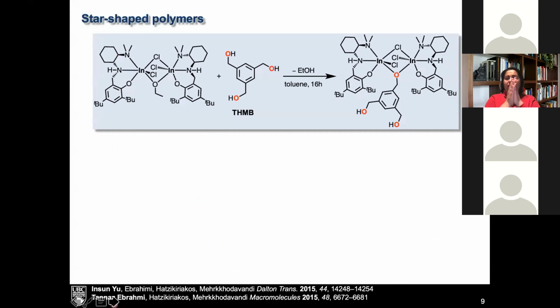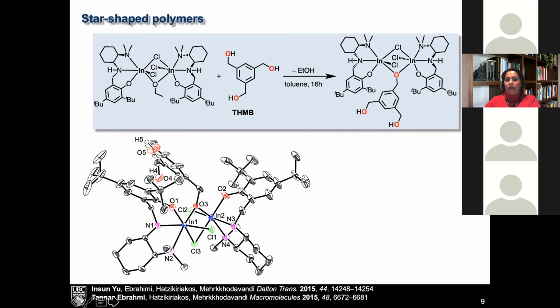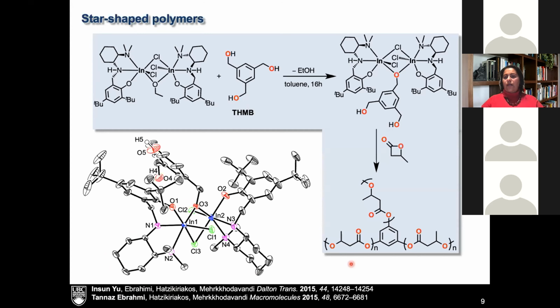The reason that it's controlled has to do with the asymmetric nature of this alkoxide and the chloride. And we can just swap out this alkoxide with any other alkoxide. So here I have an ethoxide bridged, so two indium centers, a chloride bridged, and ethoxide bridged. You can just add a different alcohol, in this case this triol, and it's very easily swapped out, and you form ethanol as a byproduct, and you form this compound. You can form it in situ, and this species is what leads to the formation of these beautiful tri-armed polymers.